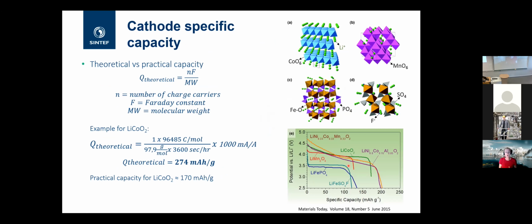Another factor that's important to keep in mind is the cathode specific capacity. Each material has a theoretical capacity. That doesn't mean that you're able to utilize that in a practical battery cell. The theoretical capacity is quite simple to calculate. You take the number of charge carriers, multiply by the Faraday constant, and divide by the molecular weight. I've given an example here for the lithium cobalt oxide, where you have a theoretical capacity of about 274